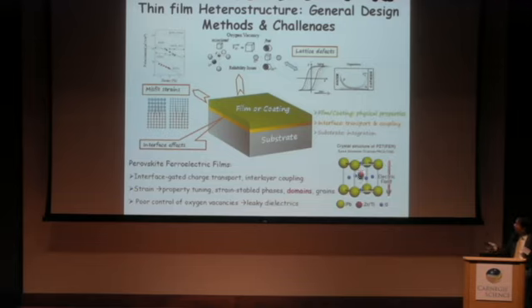Knowing this general background, for perovskite ferroelectrics, you can design from 3 different major approaches. First, about interface. Interface, of course, is a gate that controls the charge transport. And sometimes when you have multilayer thin films, you're going to utilize the interlayer coupling to achieve some functionalities that you won't get in single-layer films. And strain is the most important effect that the substrate imposes on the film. You can tune the property of the current phase, or you can achieve some new phases, so-called strain-stabilized phases.